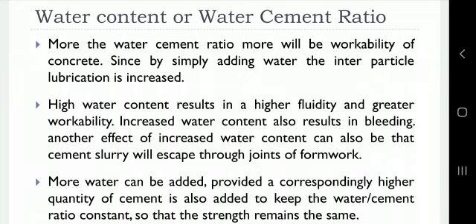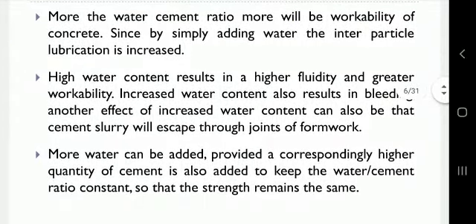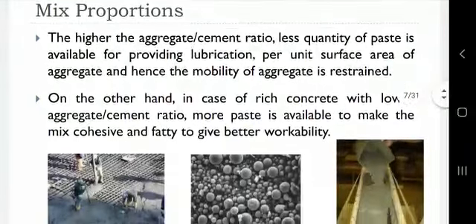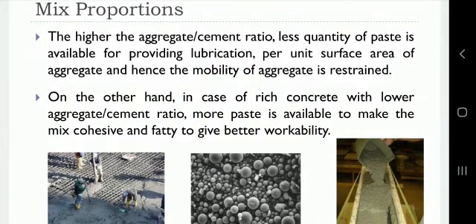More water can be added provided a correspondingly higher quantity of cement is also added to keep the water-cement ratio constant so that the strength remains the same. The higher the aggregate-cement ratio, the less quantity of paste is available for providing lubrication per unit surface area of aggregate, and hence the mobility of aggregate is restrained. In case of rich concrete with lower aggregate-cement ratio, more paste is available to make the mix cohesive and fatty to give better workability.